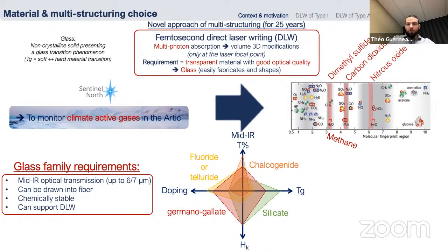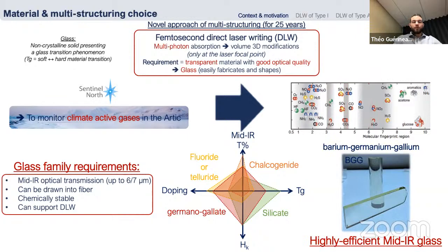And then the glass family that we are interested in here today are the germanogallate or gallo-germanate glasses. Why that? Because they have a hardness very close to the silicate glasses, a TG that can be above 800 degrees. They also can solubilize a high concentration of doping elements, above 10 mol %, and their mid-infrared transmission can reach 7 micron. The more specific glasses that we are interested in today are the BGG, the barium germanium gallium glasses. And so for these 4 properties, we consider them as highly efficient mid-infrared glasses.